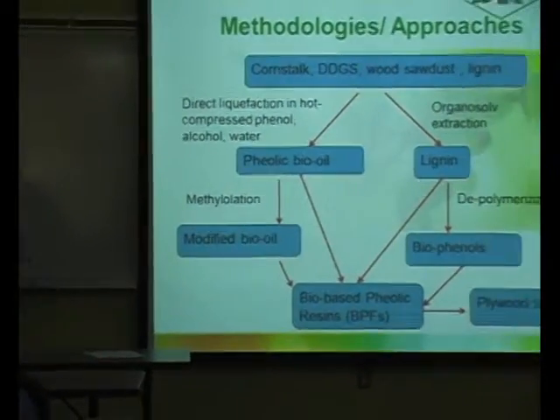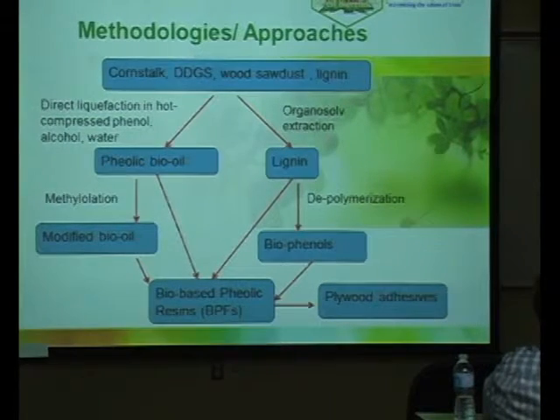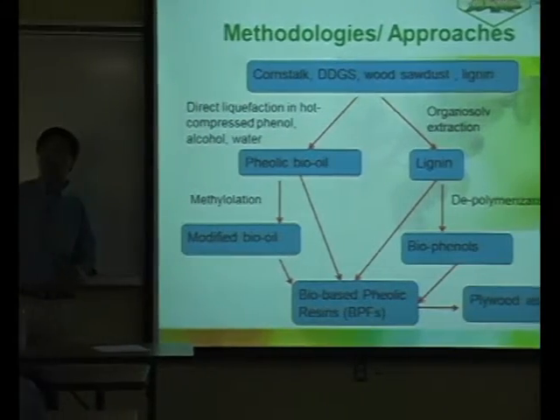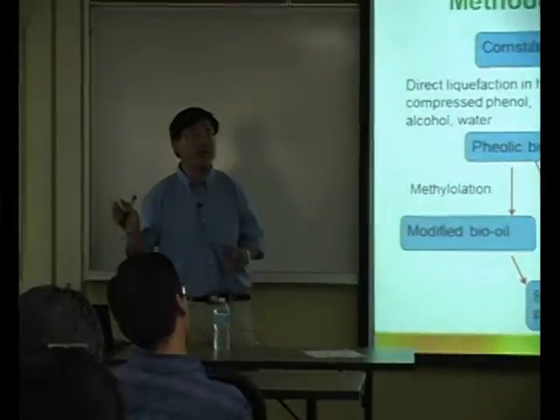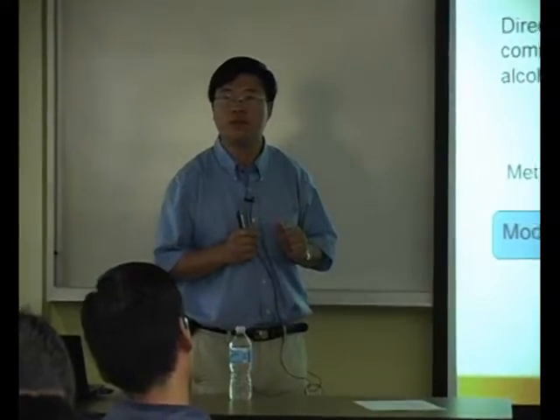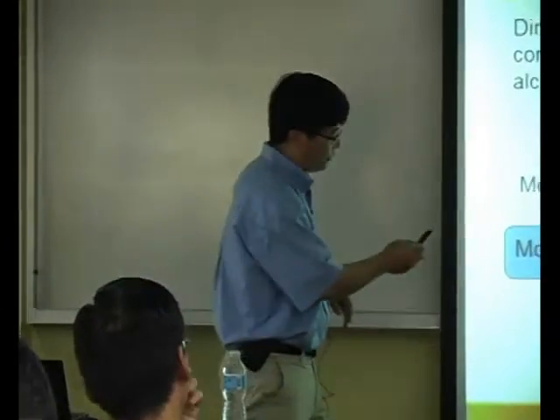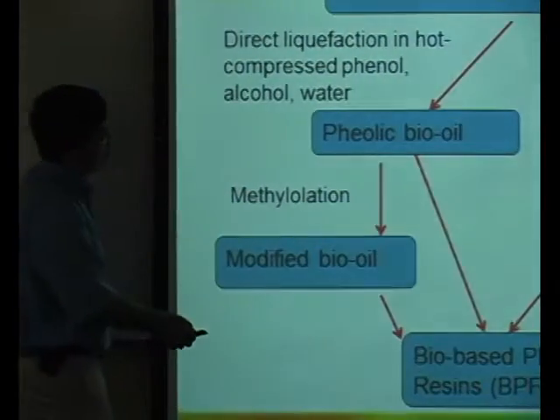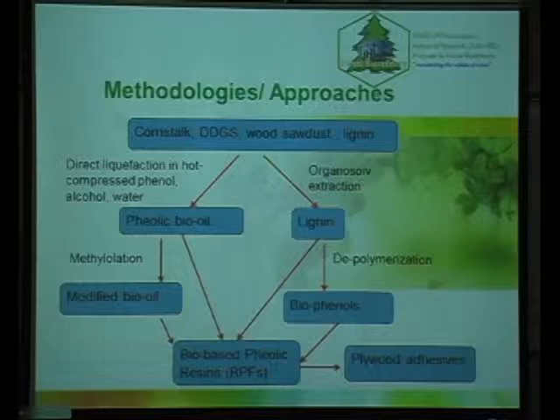Another approach we think is more promising is to separate lignin. In the biofuel industry, they do not lack lignin. They want to get rid of lignin and use the cellulose to produce sugar. So we can utilize that lignin. We can get lignin out of biomass and then do depolymerization. We purposely break down the polymer to make monomers, dimers, or other small oligomers, and then we can produce biophenols. Those biophenols can have higher reactivity, and we can get a complete replacement of phenol in the resin industry. So that's another major application for lignin, to produce bio-based phenol and resin adhesive.